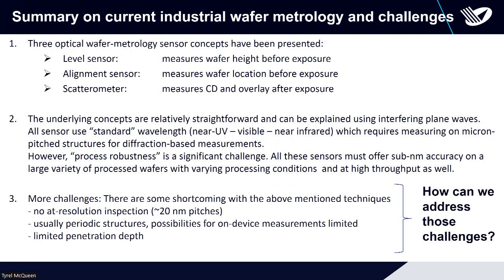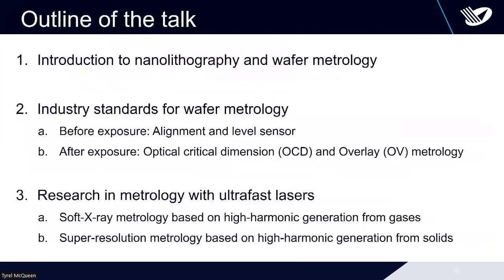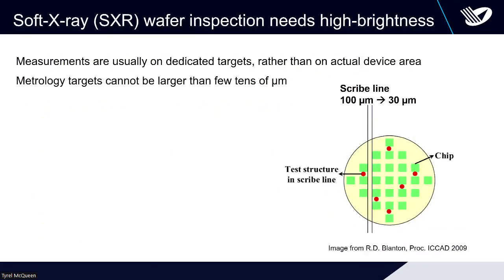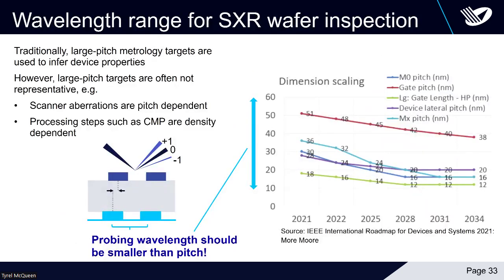And if you go into the soft X-ray range, the penetration depth becomes more favorable. In the hard X-ray range, you can measure in transmission through several micrometers. In the soft X-ray range, you can deal with a few hundred nanometers, which is already pretty good. So soft X-ray seems to be one of the ways to go, and that's one of the main parts of my research. In soft X-ray, the idea is still to work with scribe lines and dedicated metrology targets, but now at resolutions of 20 nanometer pitches. The pitches we're dealing with are illustrated here. It's currently somewhere between 14 and 45 nanometers, but that's going down to below 10 nanometers in the next years.